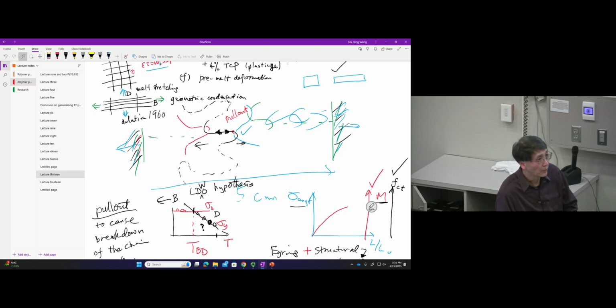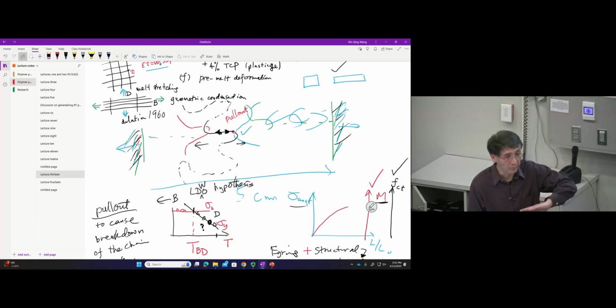You add a few percent of a plasticizer or solvent, a small molecule. Generally, adding such a small molecule plasticizer will lower the Tg, so mobility will improve. So according to any traditional view, this added plasticizer should make ductility occur even easier. But the opposite was found. Adding a few percent, this ductile PMMA turned brittle. This is really contrary to any common sense, or the traditional view of brittle-ductile behavior. So what's the interpretation, or rather, how do we understand it within our current framework?